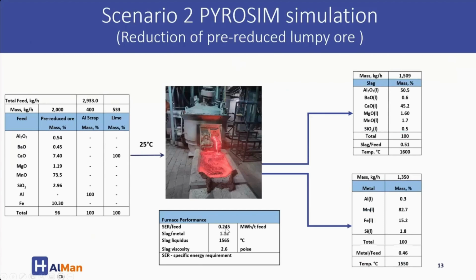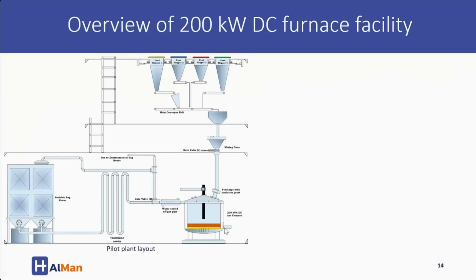We're hoping to achieve 82% manganese in the metal. You can see for pre-reduced ore, the specific energy requirement is predicted to be much lower than when smelting slag.